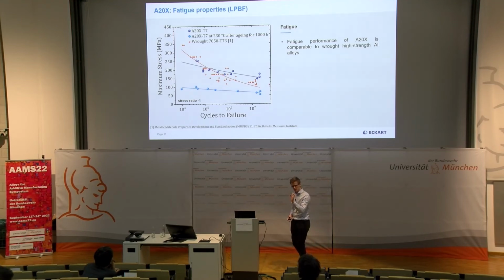The points in bright blue were generated by taking those test bars and aging them for 1000 hours at 230 degrees Celsius and then testing them at 230 degrees Celsius, which is a very extreme example showing that at least some fatigue strength is still preserved under such severe conditions. Now what I have included here is very simple data on wrought aluminium alloy 7050, and what we see is A20X has fatigue performance that is comparable to conventional high-strength aluminium alloys, which makes it suitable for